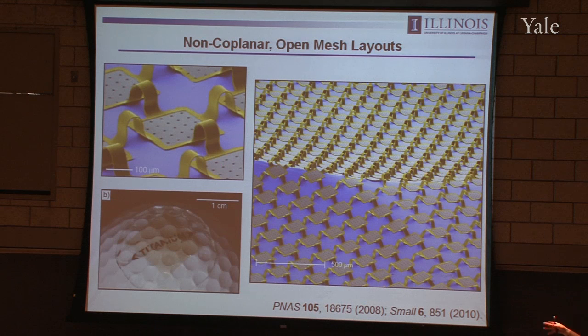And as a result, when you relax that initial pre-strain, they delaminate and pop up out of the plane. And so if you do that, you can create circuits that you can stretch maybe 100, 200%, much more like a rubber band, piece of latex or spandex, for example. And you do it in a way that really strain isolates the silicon. These silicon islands don't see much strain at all because the strain is being accommodated by these bridge-shaped interconnect ribbons, essentially.